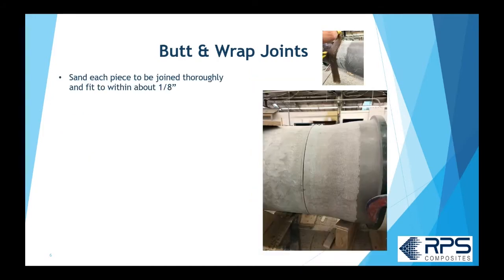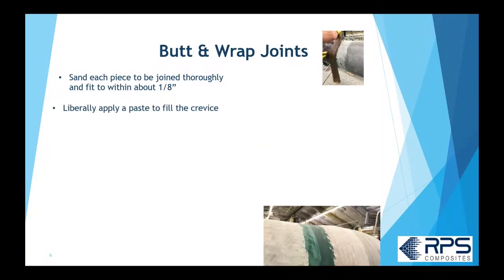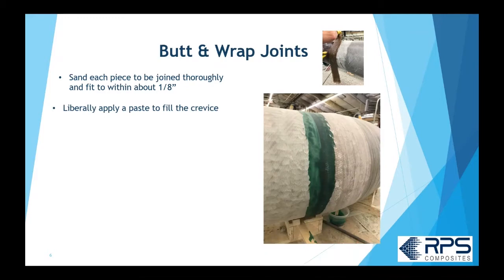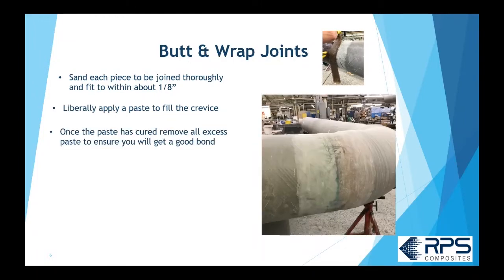So basically, to make a butt wrap joint, what you have to do is thoroughly sand the top coat, which has wax in it, off the pipe, fit the pipe to within about an eighth of an inch. You're going to apply a crevice paste, and I say liberally here because you're going to see in the next step, we remove the majority of that crevice paste. So I liberally apply crevice paste and then I grind off, once it's cured, all but the actual crevice. So all the little crevices are filled in, but it's going to get you a good bond that way.